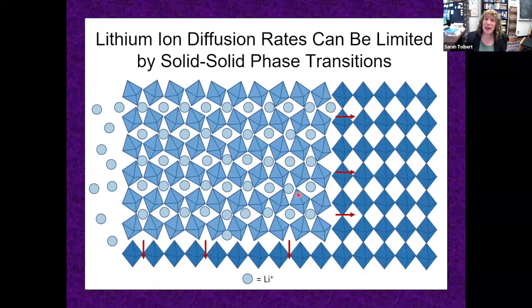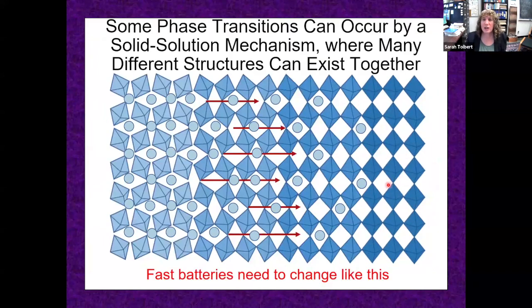If instead of this phase transition between two different crystal structures, we could instead have a more relaxed material that could accommodate every crystal structure, something we call solid solution behavior, we could go from empty to full through a variety of intermediate structures. And now the lithium can easily hop from empty site to empty site and move through our material. And so fast batteries need to change like this.